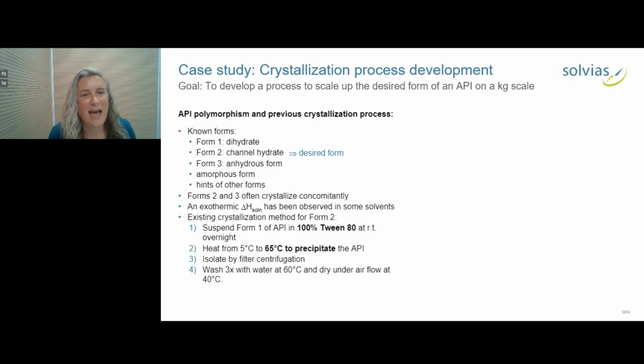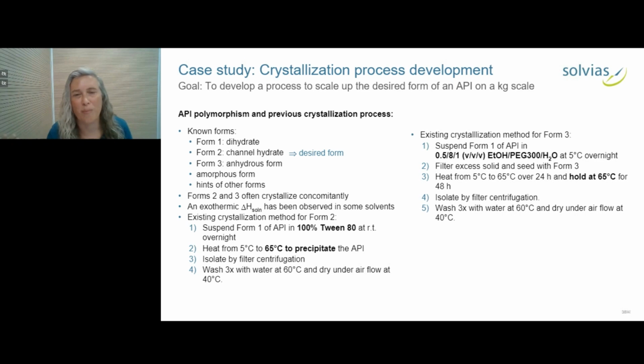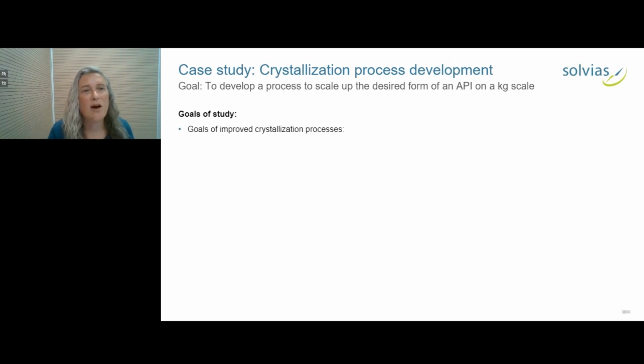And the method that they had for form 2 involved the surfactant and emulsifier Tween 80, and it was a heating crystallization. And they also had a method for form 3, involving a mixture of ethanol, water, and a liquid polymer, polyethylene glycol, with a molecular weight of 300. It was also a heating crystallization. But the yields of both methods were suboptimal. So they wanted improved processes, actually for both of them, but I'm going to talk in the rest of this webinar just about the case for form 2, because that was the form that was ultimately selected.